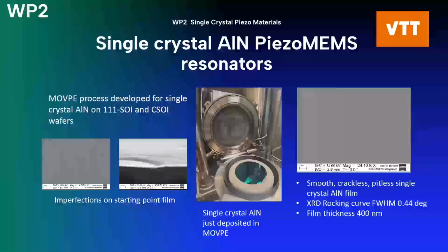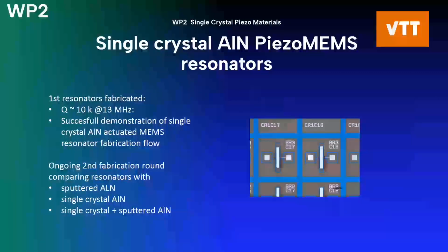So we have, using the Aalto tool in Micronova, developed an MOVPE process for depositing aluminum nitride up to 400 nanometers in thickness on the cavity SOI wafers, and it produces very smooth and crackless aluminum nitride film. The XRD rocking curve width is 0.44 degrees, which is significantly smaller than in the sputtered films. First resonators have been fabricated, epitaxial aluminum nitride on cavity SOI, Q value around 10,000 at 13 MHz, nothing spectacular as such, but it's a completely new way of manufacturing the devices. And now we have a second round ongoing with comparable resonators using sputtered aluminum nitride, epitaxial aluminum nitride, and a combination of those two, so we can really compare them.